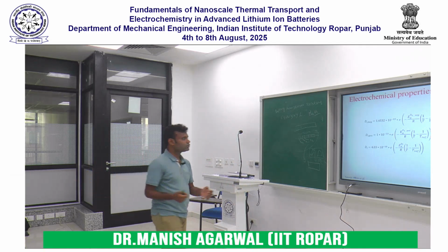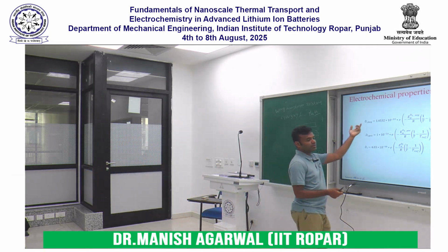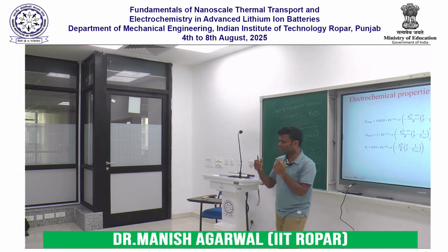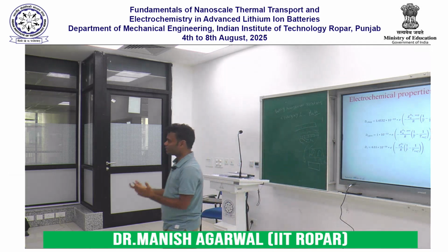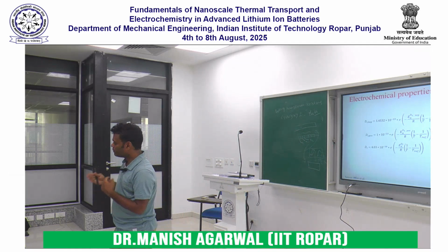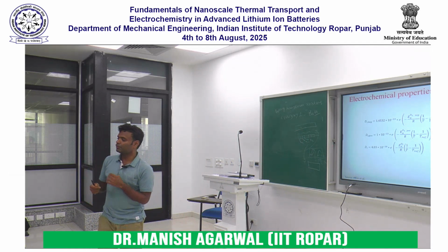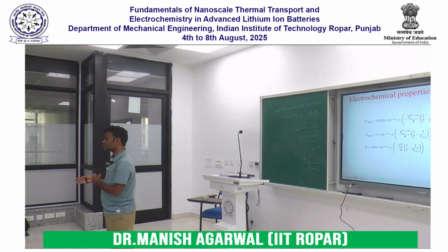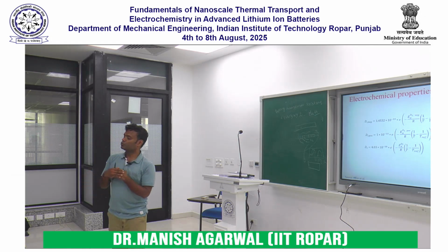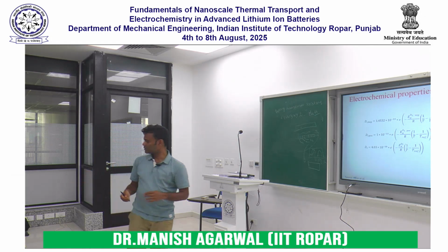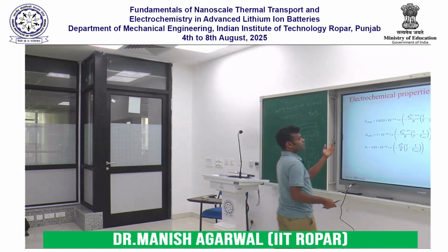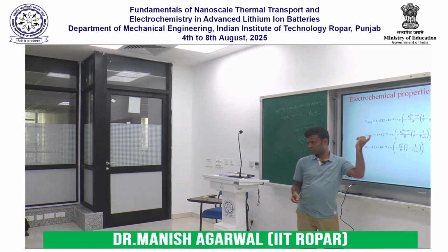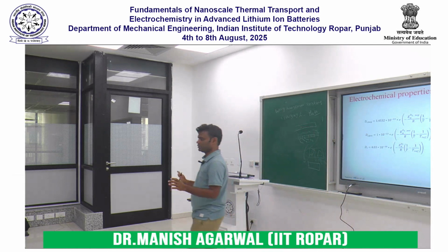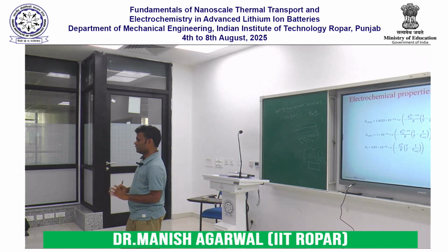But just to stress, all the things that we have taken, diffusion coefficient, conductivity, each of these parameters do depend on the temperature, right? So in general, if you have some explicit relationship with respect to temperature, that is well and good. But if you do not have a special relationship, in general the default choice is the Arrhenius equation for all the parameters, unless you have some extra information.